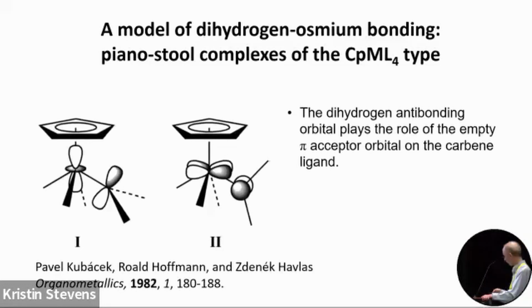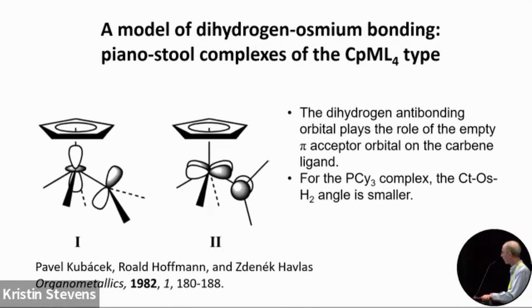And that rotates by 90 degrees if we have some kind of bulky ligands here that reduces this angle. And so now by flipping 90 degrees, the dihydrogen can overlap with the DXY orbital. And so we get a lot of electron density into the antibonding orbital, giving us a long 1.3 angstrom bond length, and the reason for this rotating. There continues to be a lot of interest in dihydrogen complexes, possibly with metal organic framework materials for hydrogen storage. The advantage is that we actually never break the HH bond, so it's easier to form the bond and then release the hydrogen.